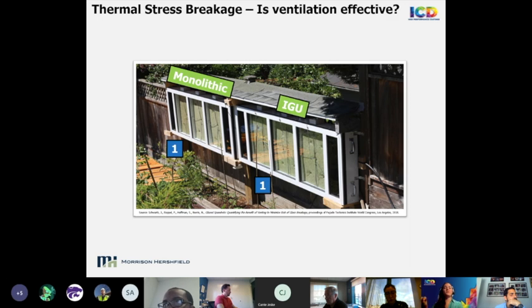So the first approach is to fully seal the perimeter of the glass, typically occurring in a 4-sided structurally glazed application. The second condition has only drain openings at the bottom, which is the traditional approach for draining spandrel. All spandrel glass applications should have some sort of water mitigation system in place to eliminate moisture buildup. And the third has vent holes at the top and drain holes in the bottom to test if you can get the same air circulation benefits that are known to occur in brick masonry, and see if this method can remove heat that can build up in the cavity.